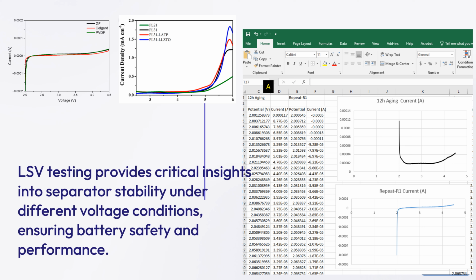If after finishing this test you repeat the same LSV test, then the curve will start from the negative side of the current and come close to 0 and then continue. So you don't need to worry, as shown in the blue graph. Some people have used this kind of graph on the left hand side. Some people have used this thick graph on the right hand side. This is the only difference if you do the test and if you repeat the test. So both give you the same results.